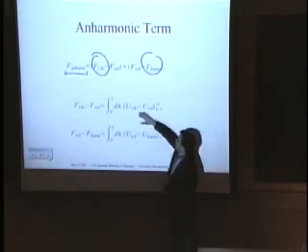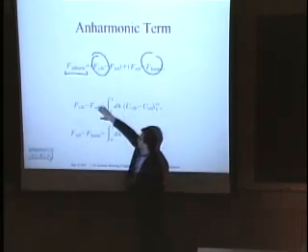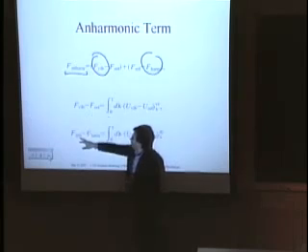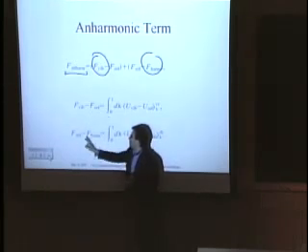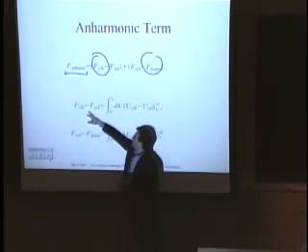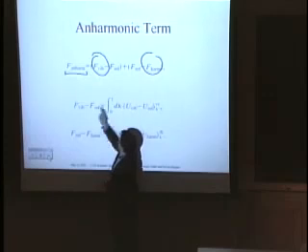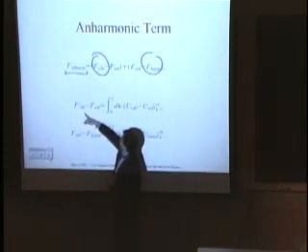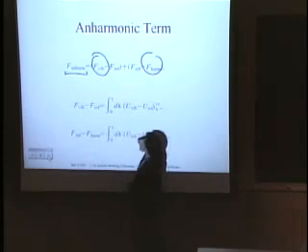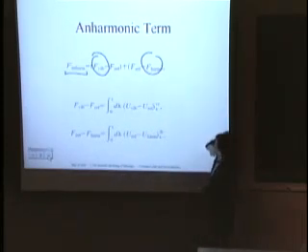And so we can break down this term in two parts. One has to do with the difference between the harmonic crystal and our reference system, and one has to do with the difference between our overall energy term here, or the overall free energy term, including nonlinear effects, minus the reference system.